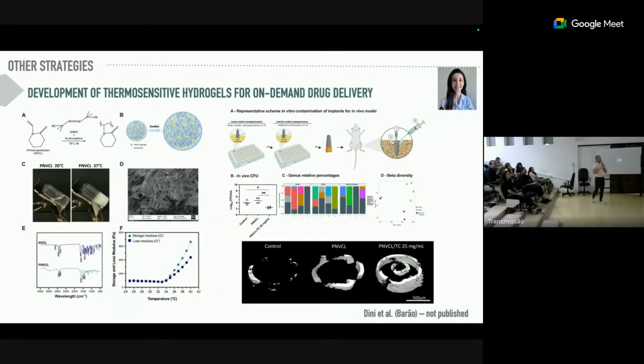We also developed some hydrogels. This data is not published yet. It's also from my previous PhD student. We developed it with the people from chemistry too, at UNESP, Araraquara. We developed a thermal-responsive hydrogel. When the temperature is 34, 35, or a little bit higher, we have the gel formation, as you can see here. We use PNVCl, and you incorporate tetracycline, and we were able to have a drug delivery system